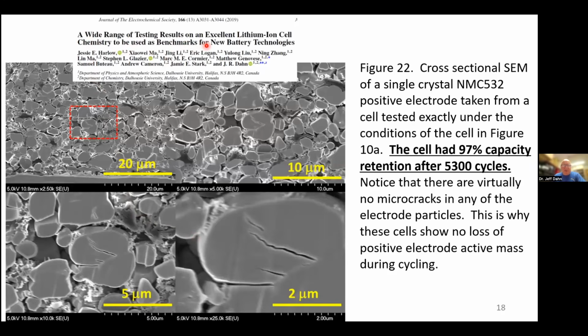So we published this paper in 2019 where we use single crystal NMC 532, and this is a cross-sectional scanning electron microscope image of the positive electrode. After 5,300 cycles, the cell had 97% capacity retention. And you won't see any microcracks in these particles. This one big one that we've been following, we don't know if this crack was here from the beginning or whether it did form during the charge-discharge cycling. But these single crystal particles really eliminate microcracking, which leads to some of the problems in cells.